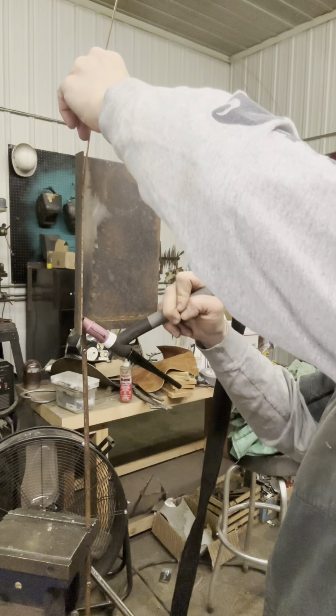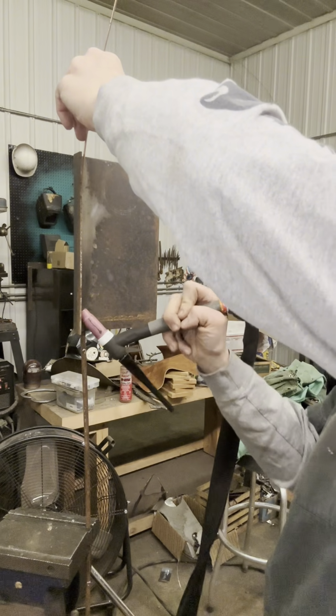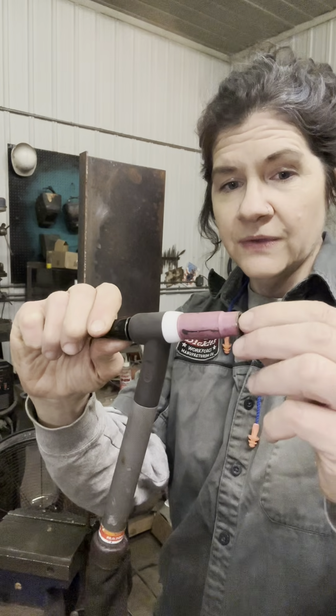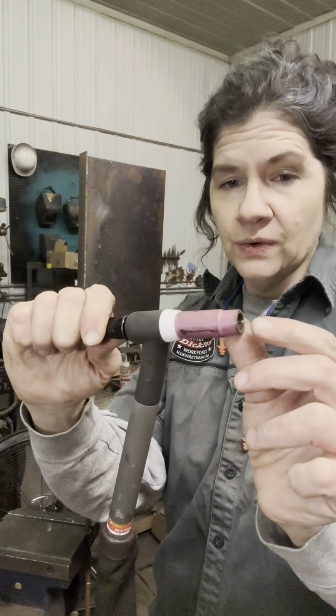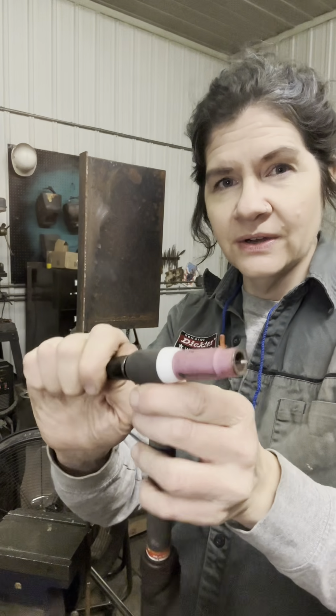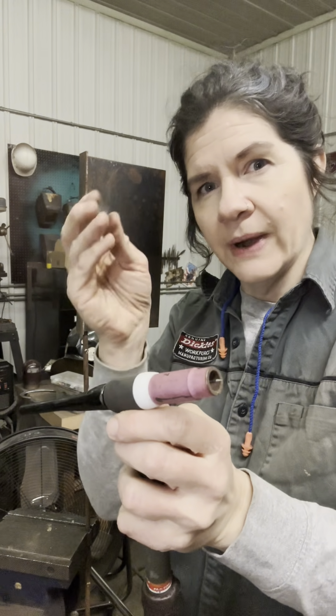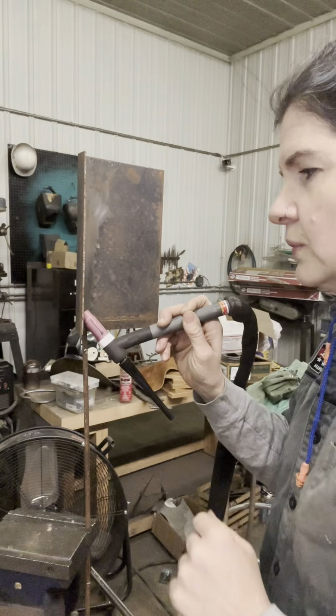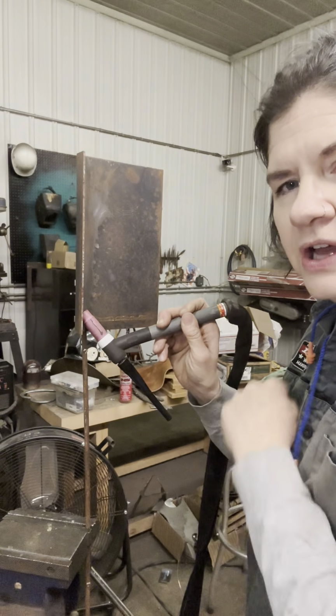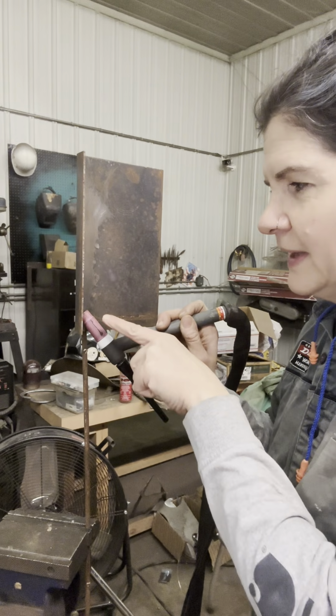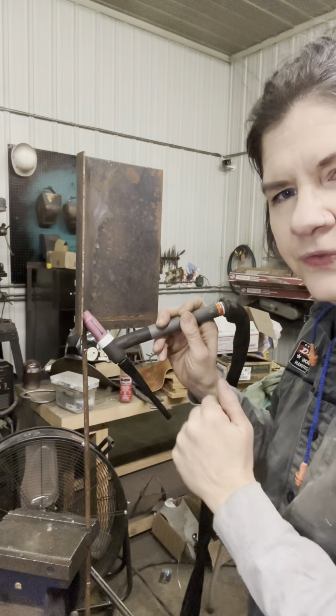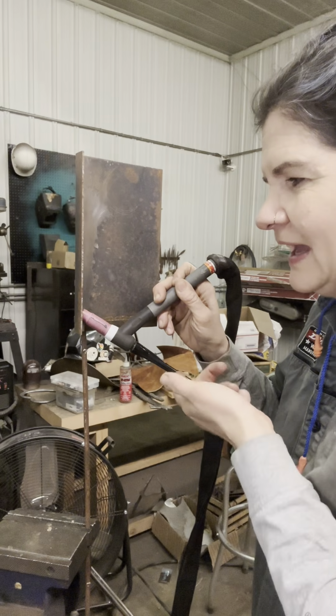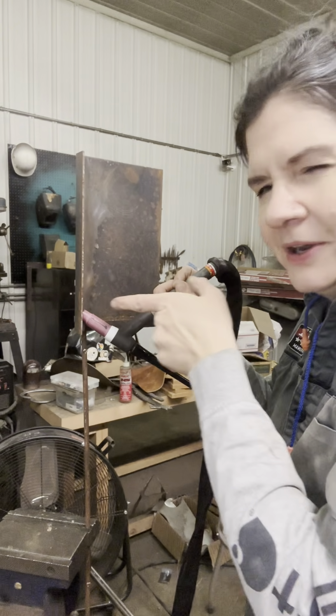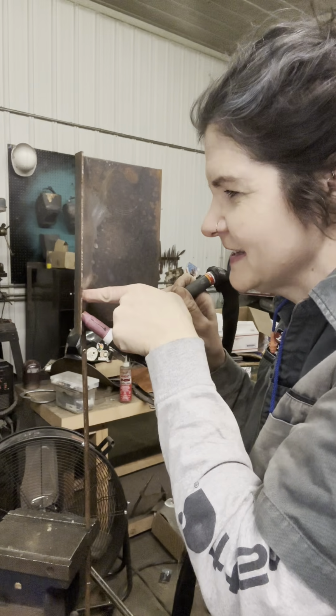When you have your angles right, you can just walk it along and burn off that rod, turn it into a weld. If your tungsten stick out is too short, you're going to drive the heat into your material instead of up a little higher where the rod can burn off and become a part of things. Rather than having an angle of burning off kind of like what I've got here, now that my tungsten's back in too far, I have to kind of pick up the end of my torch to get my puddle sticking in the center, in the dead center where I want it to be.